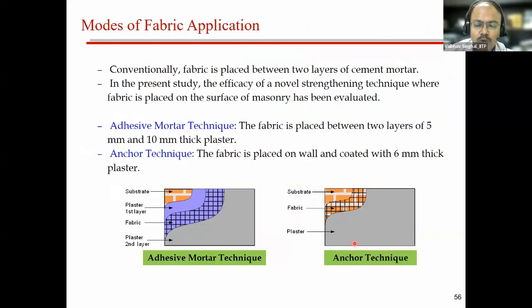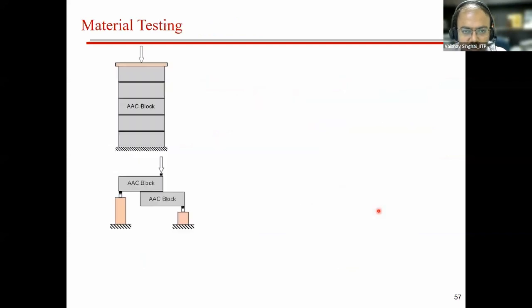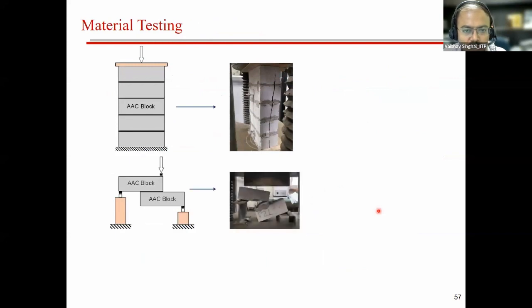So as I said, two types of techniques we have used here. In the first case, we first applied a layer of adhesive mortar, the polymer mortar, and then simply put the fabric over it, and then put another layer of simple cement mortar. In the second technique, which I'm calling the anchor technique, the fabric is directly placed over the surface, and then we install the anchors at a few locations and then cover it with the plaster.